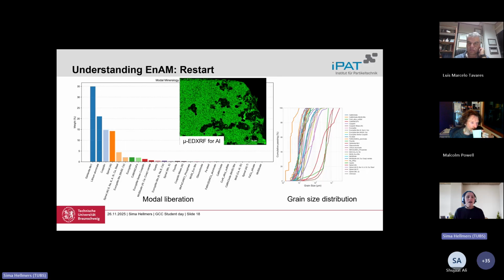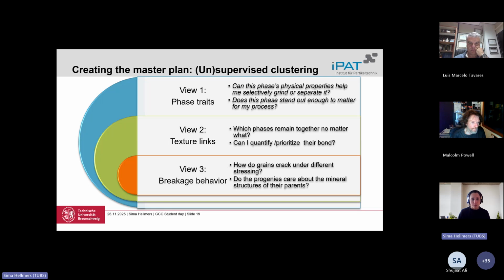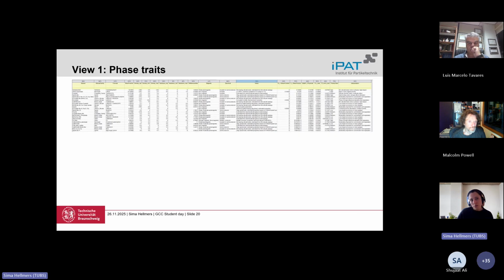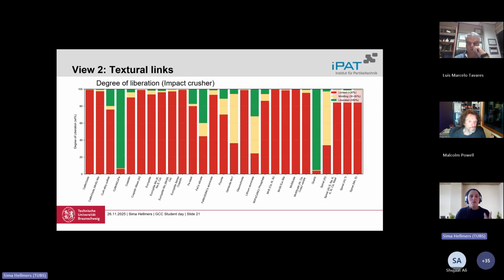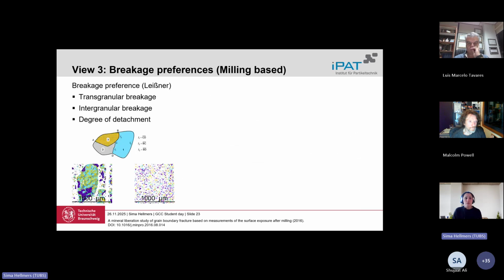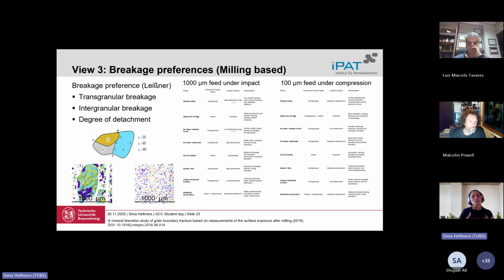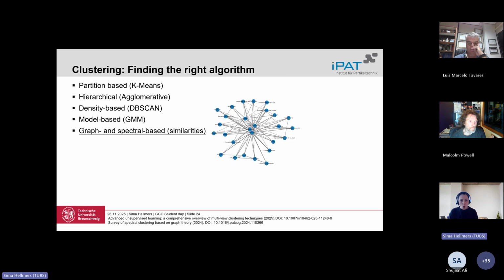Okay, sorry. So to sum it up, here we use this texture analysis to develop a method that clusters all the phases together, and then based on these, we can look at different values and put different phases together and design the process again. So we can use three different views, from the phase traits, from the textural links, and from the breakage preferences, to see how the process changes based on these points, and then use different clustering methods like K-means and graph-based similarities, and build our view.